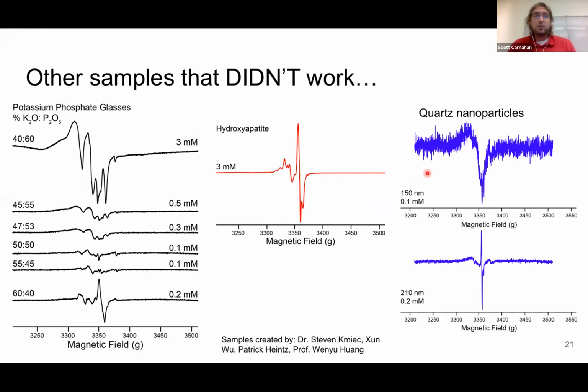One other thing we tried to do was reduce the particle size of quartz. So we had Xun Wu from Wenyu Huang's group synthetically make smaller quartz nanoparticles of 150, 210, and 70 nanometers. What we saw was it was hard to get radicals to stay in these very small samples. We think we know why, but we weren't able to get it to work. So we thought, what other way can we reduce particle size?